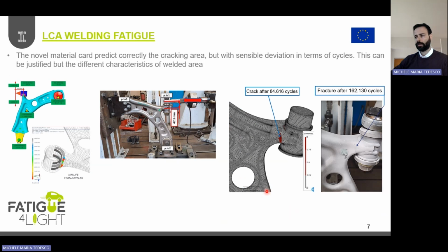The second test was always about the fatigue, but in this case for the welding of the bush that we have in this component. So we did the test like that. We block here the component, we block also here, and here with a displacement of 47 millimeters, we apply a load in order to stress the welded area. Here you can see the simulation results, and the crack is in this area. And here the real component, in which the area is the same.